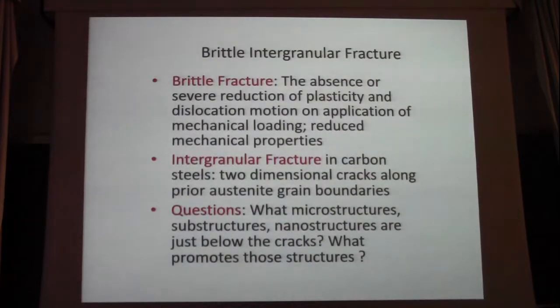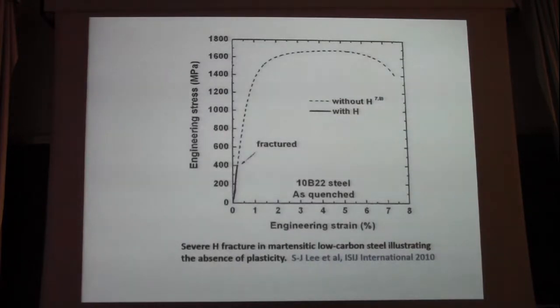Steovine indicated yesterday, at least in terms of hydrogen cracking. And here's a really bad example of hydrogen charged low carbon steel, 10B22 steel. This is steel used in automotives now. In other words, automotive steels, for safety considerations, need martensite, need the strength that comes with martensite. If you charge with hydrogen, you know, this is a laboratory experiment.